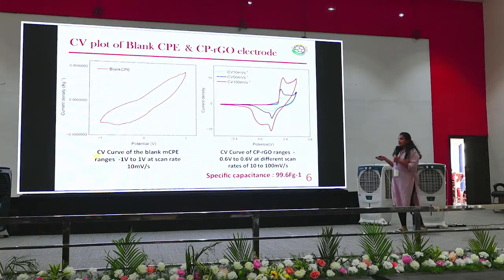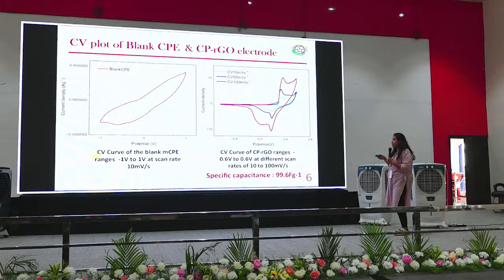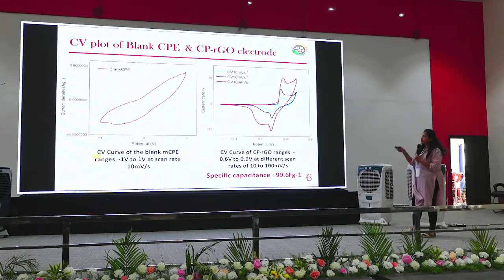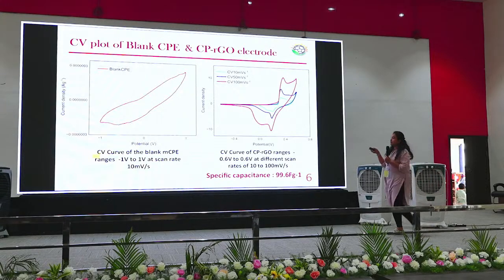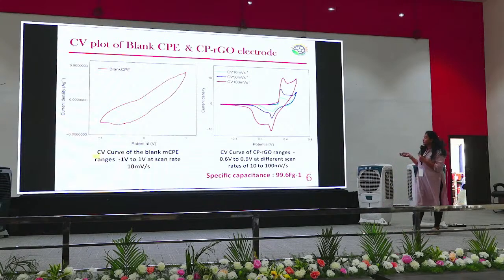And the electrochemical behavior of this reduced graphene oxide incorporated in the carbon paste electrode: the first one is the blank carbon paste electrode, which shows the CV graph in which we can visually see the potential range is very small. When compared to the RGO incorporated one, it shows a maximum specific capacitance value of 99.6 F/g.